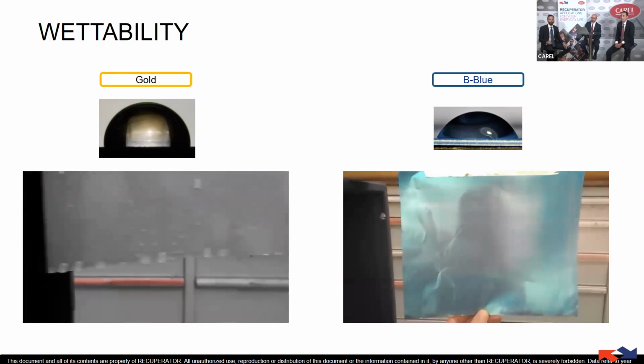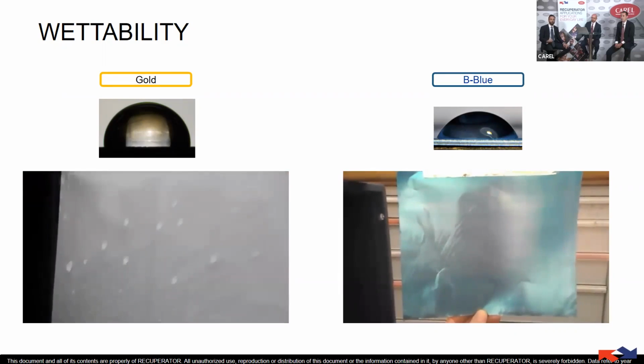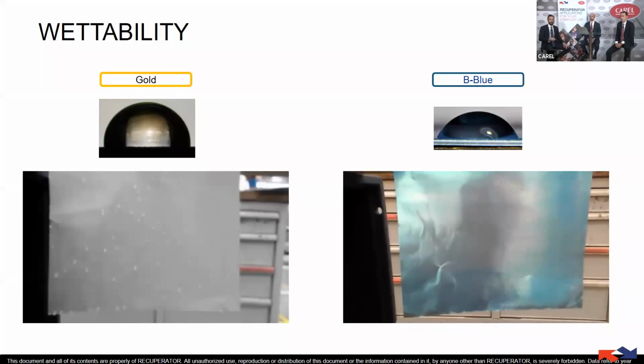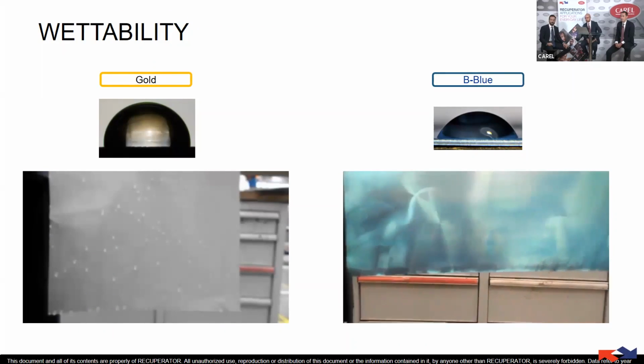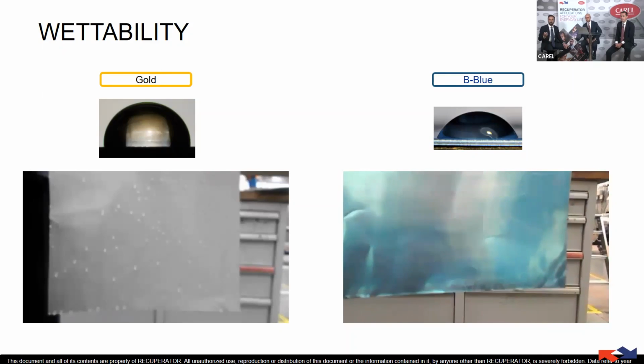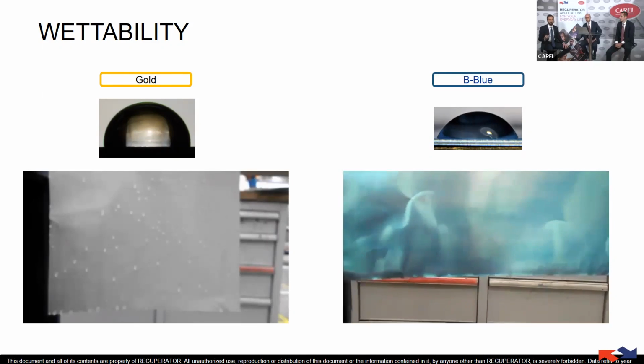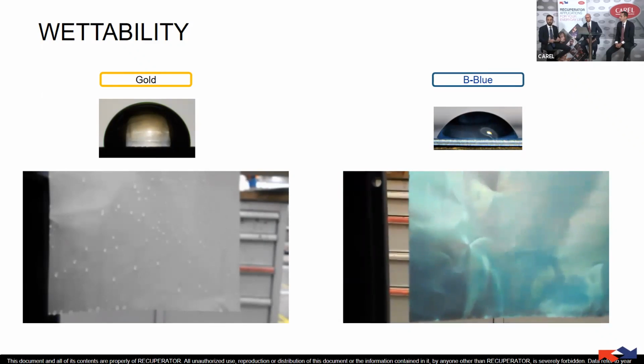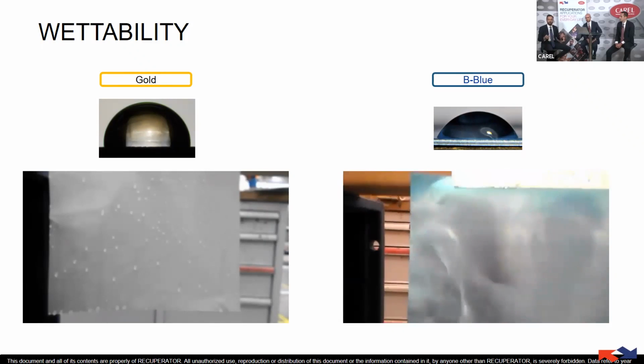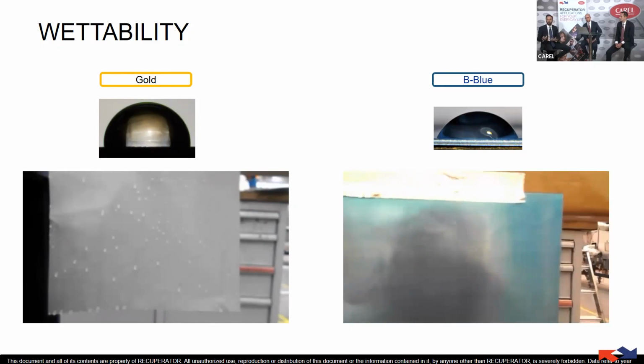Thanks to this film of water, we can have an increase of cooling capacity that we have seen before with the example, 10%, 15% more than the standard gold protection. This is really important because the way we can increase the cooling capacity without increasing the pressure drop is just by using a type of coating.